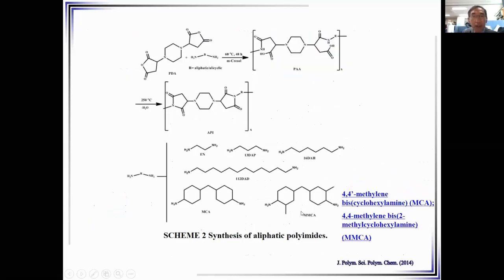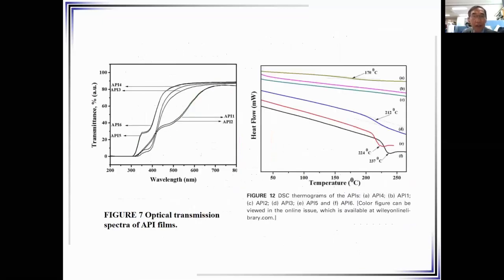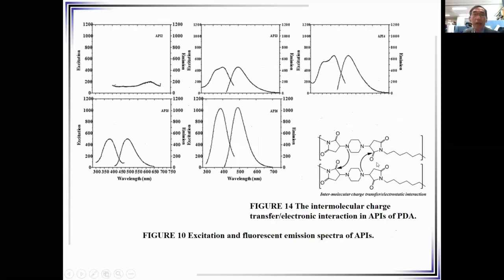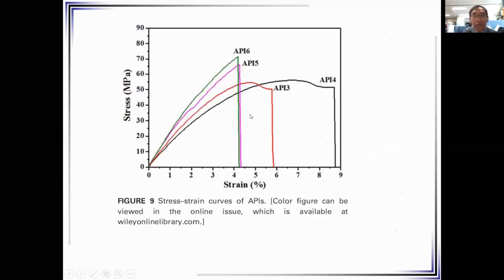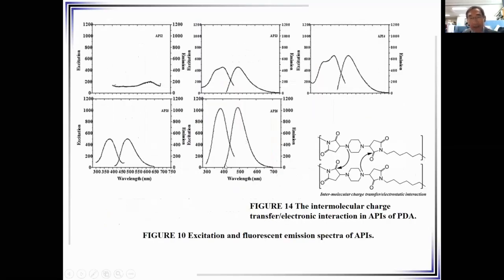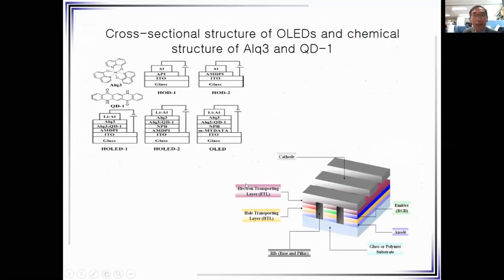By using the brand new dianhydride and mixing diamines, we could make six different polyimides. As you can see, the mechanical properties and transparency are over here. Even though not over 90%, the transparency is over 80% or 85%, not so bad. The thermal stability is also not so bad. And this polyimide has a really interesting property: even the polymers emit light. That means this can be used as a flexible substrate, and additionally as an emitting material. Very interesting.